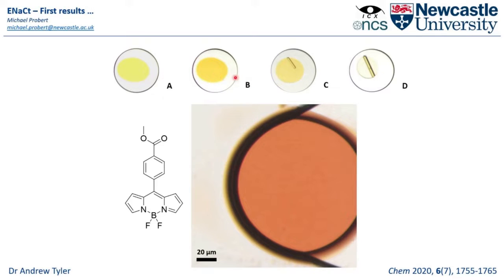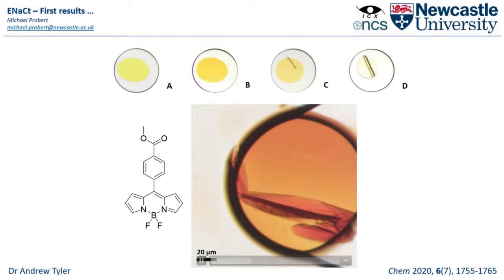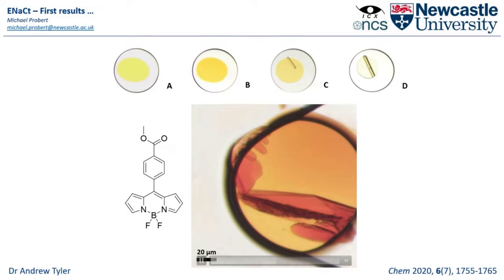And you can even see the change in colours showing the difference in concentration of our solution trapped within these inert oils. And if I show this in a time-lapse video, this is a slightly malformed droplet where the analyte has drifted across to the border of the oil, but you can still see a boundary of oil around it, and we can see crystal growth within this droplet and changing local concentration gradients within these droplets for this moderately simple organic system. And one of these crystals on the top edge was more than large enough to run in-house.